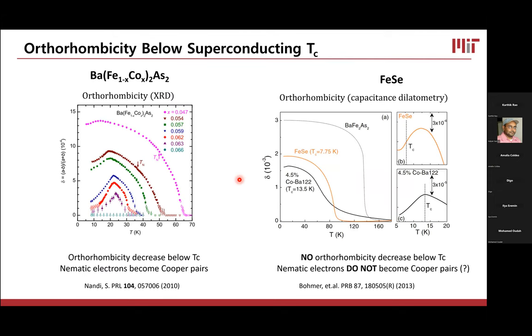The next thing that we can look at is the behavior of the lattice distortion below the superconducting transition. If we look at the iron pnictides, something very interesting happens. If we go to one of the dopings where superconductivity exists and coexists with the nematic transition, then we can track the orthorhombicity as a function of temperature into the superconducting state. Down here, we have the onset of the orthorhombicity at the nematic transition. And over here, unfortunately they're not clearly marked, but these points correspond to the onset of superconductivity.